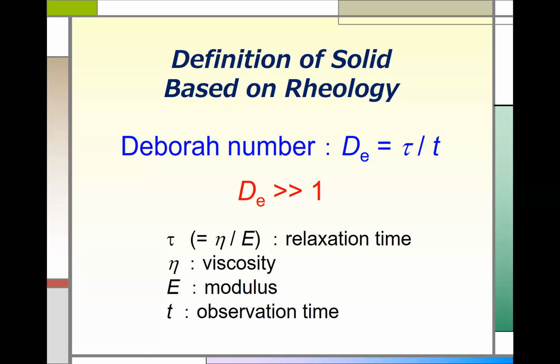However, if you take a look at the interfaces, tau can be changed. That is why I'm trying to explain what tau is and what the definition of a solid is. As I told you, tau is actually the ratio between viscosity and modulus. This is the viscous part, and this is the elastic part. This ratio is the relaxation time, and tau is actually the indicator of how fast molecules can move.